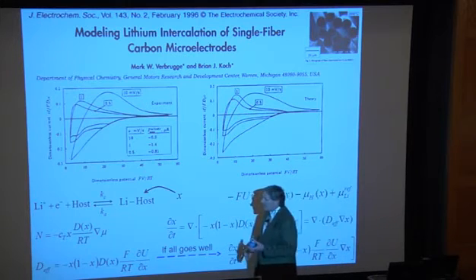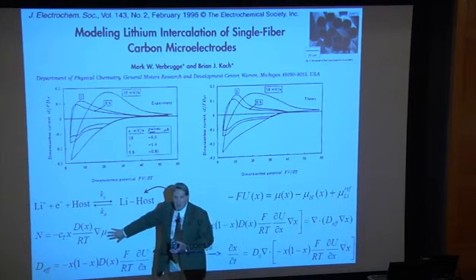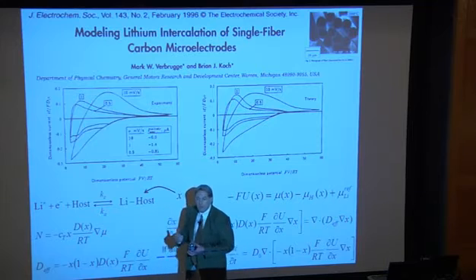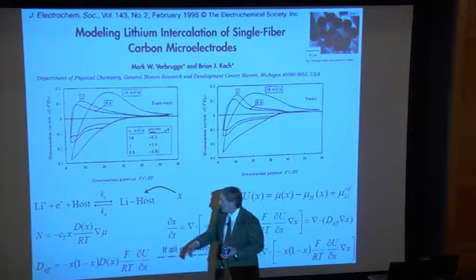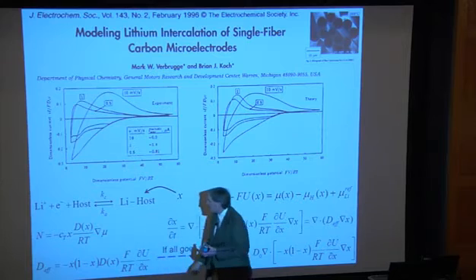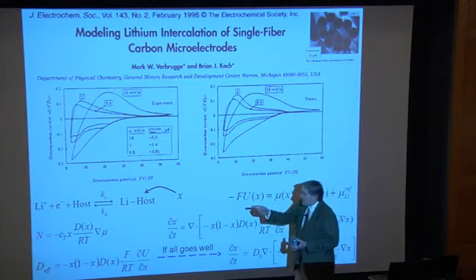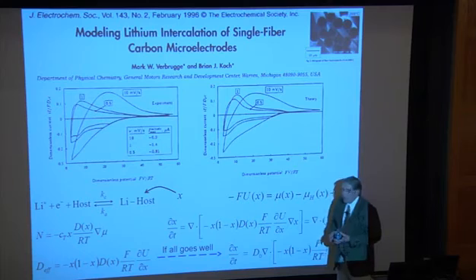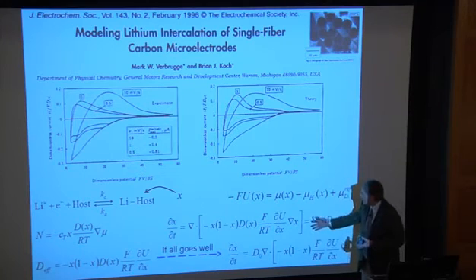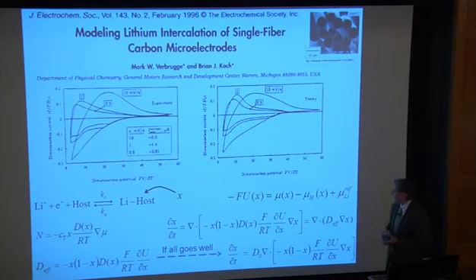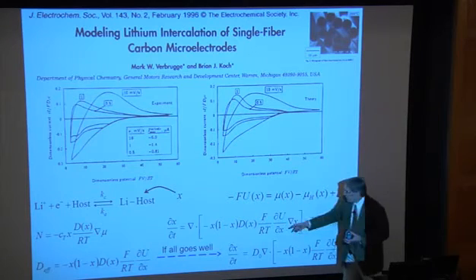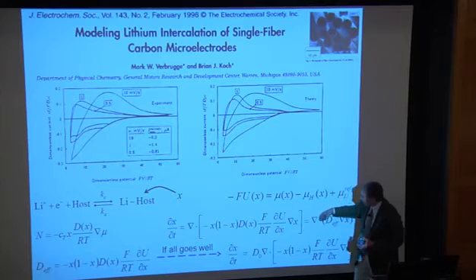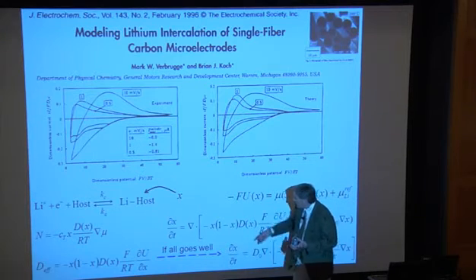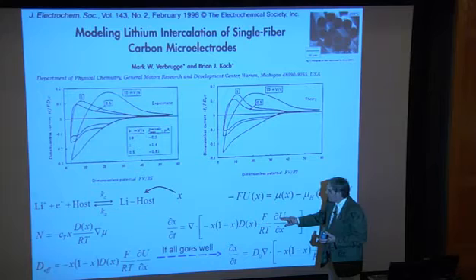If you use irreversible thermodynamics, our flux expression looks like this. This becomes Fick's law if you're infinitely dilute. If you're not infinitely dilute, you end up with this gradient in the chemical potential showing up. And when you stick that flux expression into your material balance equations, you get this expression over here for the lithium mole fraction X, and we have an effective diffusion coefficient showing up here, which would be including all these terms. And what's important to note is this quantity you can get from the open circuit potential.